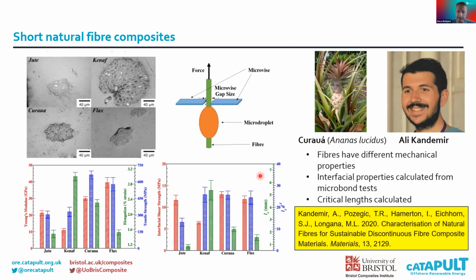And he's been looking at all sorts of different fibres: jute, kenaf, curauá, and flax. He's been measuring the interfacial properties using this setup here, where you pull a fibre between two blades and measure the force required to pull the fibre out from a microdroplet of resin. And he's been calculating some critical lengths. Now, just a quick take-home message: the curauá fibre is actually the best fibre, it would seem. It has a reasonable critical length, but it also has reasonable mechanical properties. And we found that these fibres plus flax were probably the best in terms of overall performance.